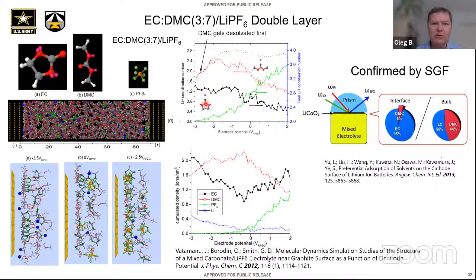So there is a preference for the EC to still be next to the lithium, even in a DMC-rich electrolyte. And I showed you a couple slides before that EC also has a slightly higher reduction potential than DMC. So taking into account the preference for EC to be in the lithium solvation shell and its slightly higher reduction potential, that leads to the conclusion that there's going to be more EC reduction, and EC is going to be a larger component of SEI, as was often reported.